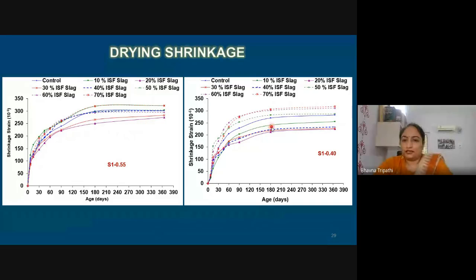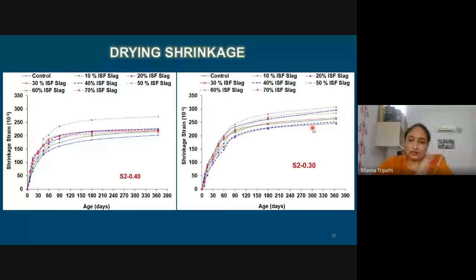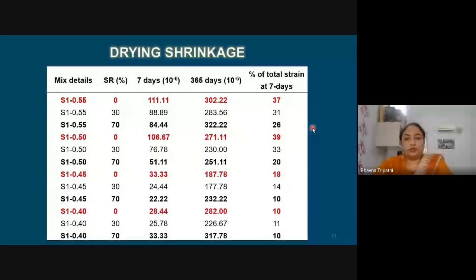What you can observe here is that largely the shrinkage strains are similar. There is not an appreciable difference. However, you can see a few lines here are different, but those mixes are different. These dotted lines are a mix of lower aggregate cement ratio. So this is an entirely different mix. In dotted lines, we can see some of the mixes have a very low shrinkage also.